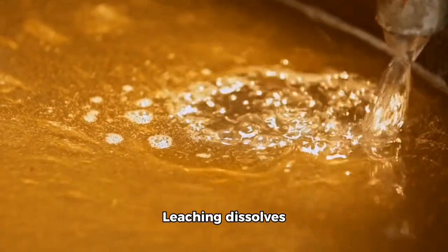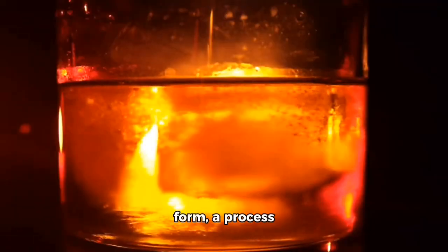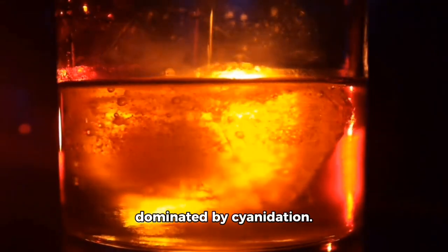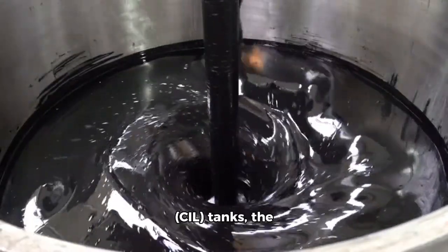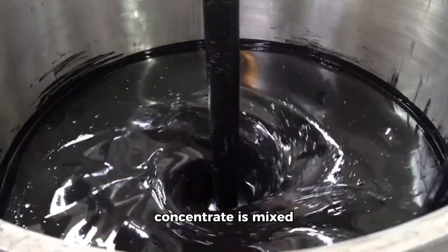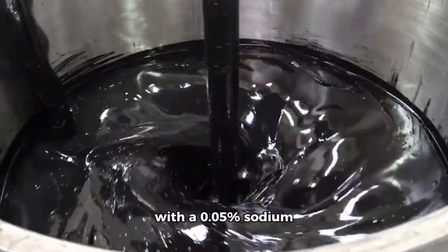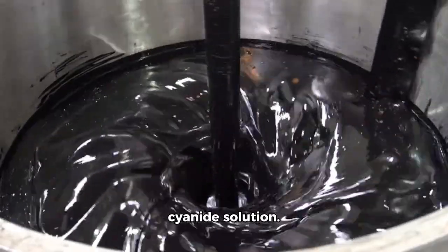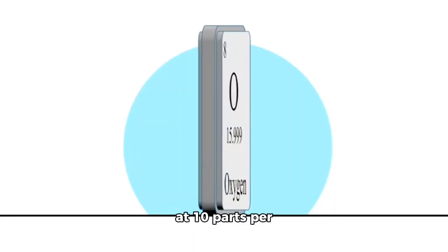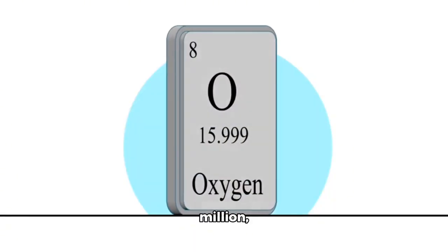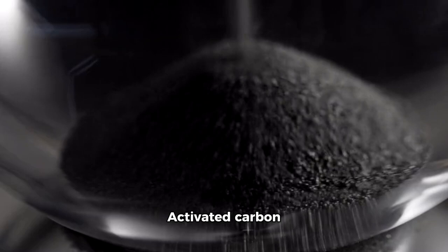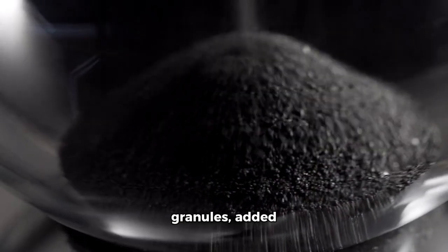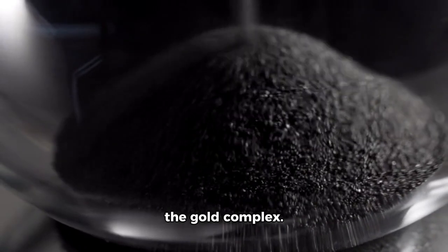Leaching dissolves gold into a liquid form, a process dominated by cyanidation. In carbon-in-leach tanks, the concentrate is mixed with a 0.05% sodium cyanide solution. Oxygen, injected at 10 parts per million, accelerates the reaction: 4 Au + 8 NaCN + O2 + 2 H2O gives 4 NaAu(CN)2 + 4 NaOH. Activated carbon granules, added directly, adsorb the gold complex.